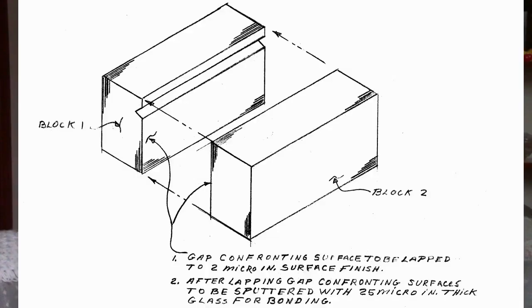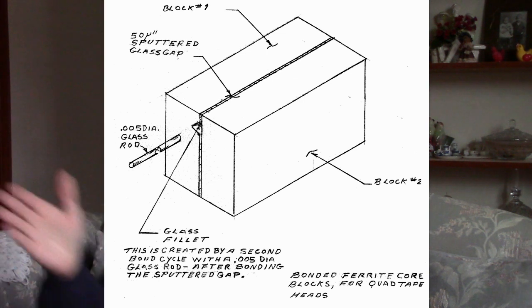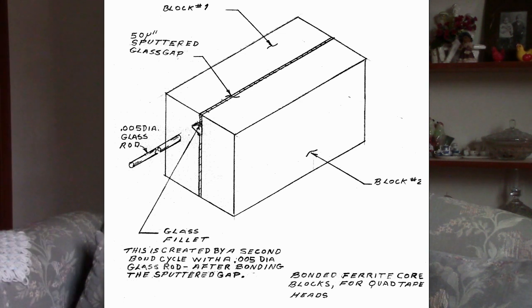In this case it would be the confronting surfaces of the two pole pieces, the gap confronting surfaces. And over a period of hours, you build up a thickness of glass on each of the pieces. Then the next step is you would put that in a clamping jig and heat it up in a vacuum furnace. And that would bond your two halves together, glass bonding. Now that's a very overly simplified explanation, but